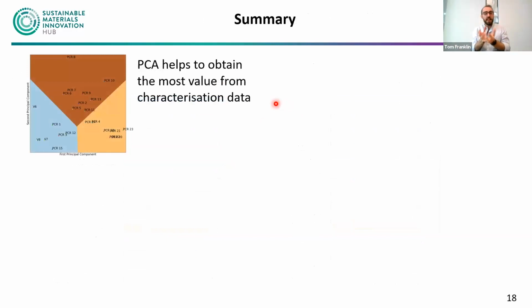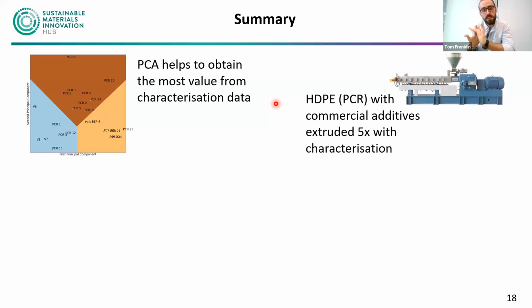But to tie everything together, we looked at principal component analysis as a really useful tool to extract as much data as we can when you have such a vast and complex data set. Using PCA to simplify that and to extract the key features and cluster your resins and your data has been a really powerful tool. Building upon that, if we look at some of the resins that have been clustered and we extrude them with commercial additives, in this case subject them to 5 extrusion cycles and characterize that, we can see that we generate even more data.